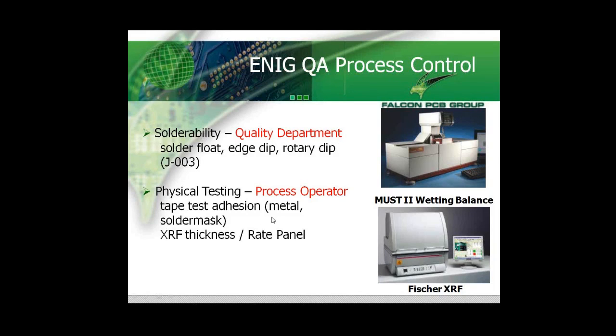These will be standard on the metal and on the solder mask, just to make sure that we haven't had any problems with the damage of the adhesion of the solder mask, and to ensure, of course, that the metal, both the nickel and the gold, are adhering properly to the copper below. What we also do, XRF measurements are taken on the rate panel and on sample boards. Now, although these are spot checks, we do tend, of course, to rely heavily on the XRF measurement for the thickness deposits.